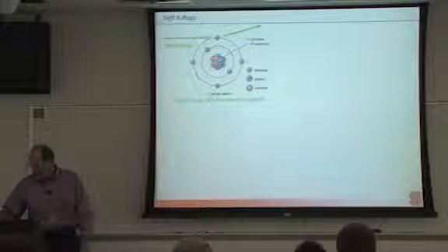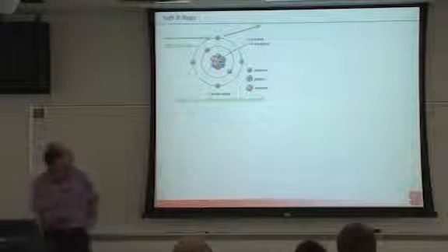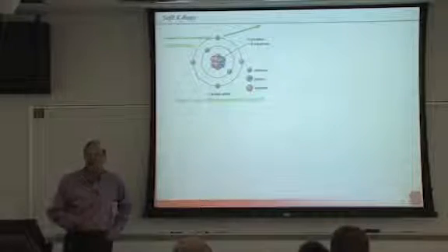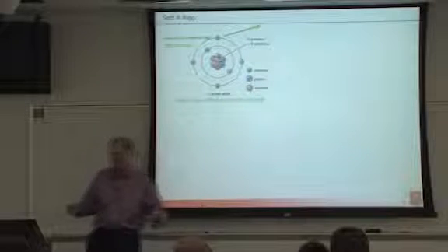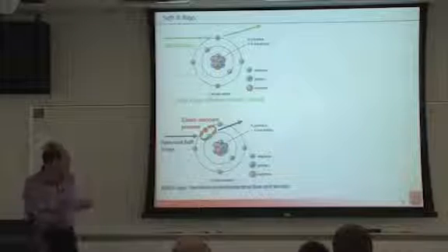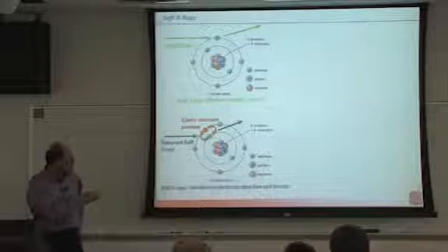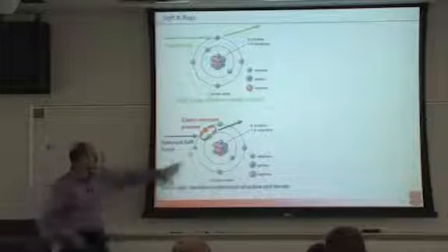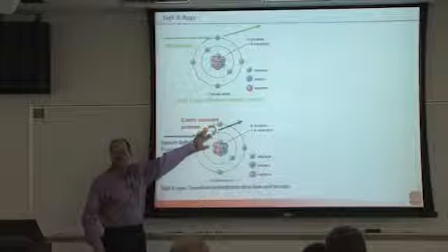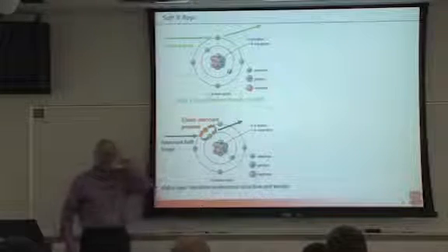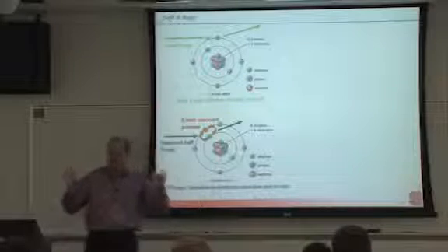What's unique about soft X-rays relative to hard X-rays? With hard X-rays, I only measure the number density of the electrons, essentially because that is what I scatter from. With soft X-rays, near the carbon atom, I can pick an energy where I basically have a virtual transition to an unoccupied state, and that is why it's called resonant, okay?